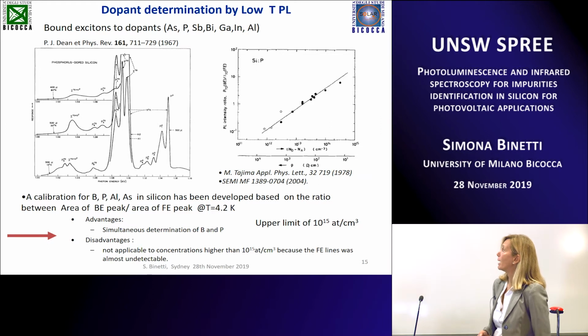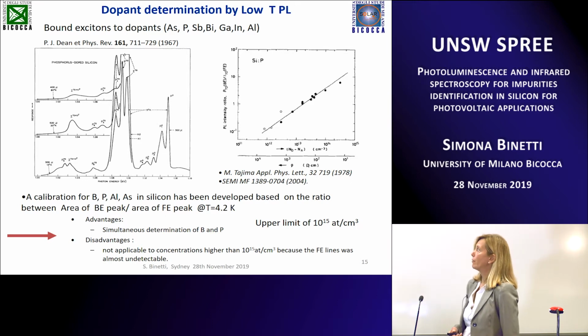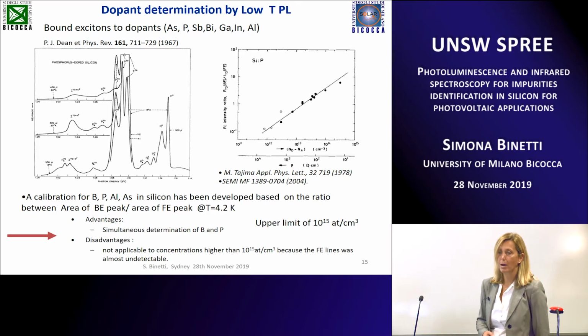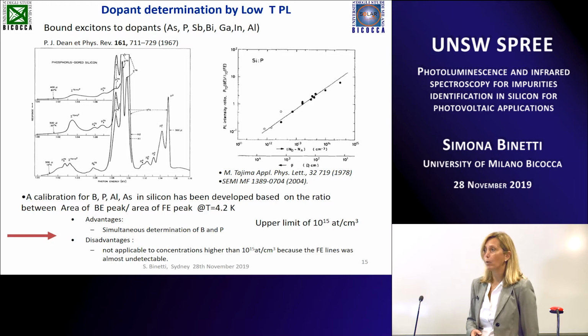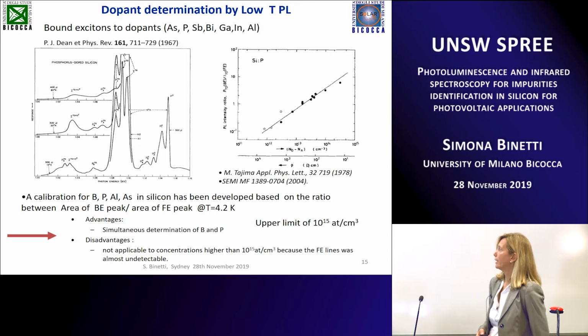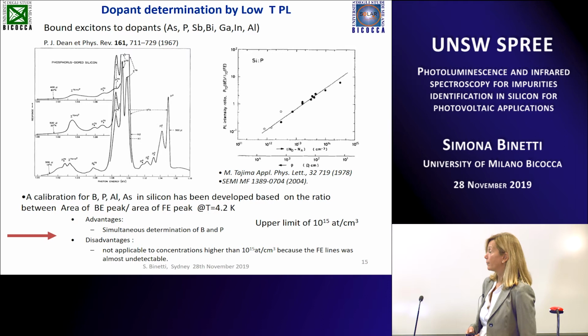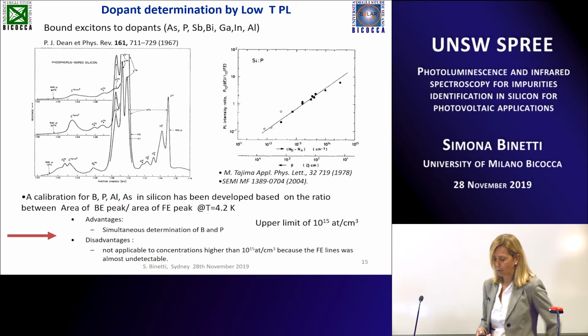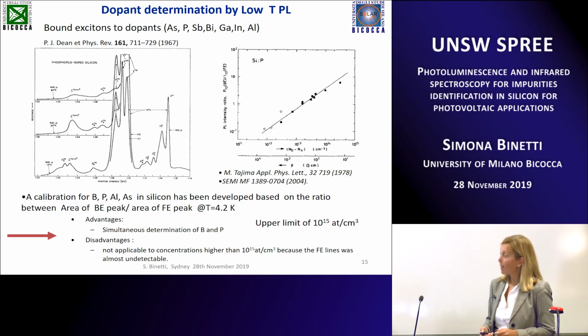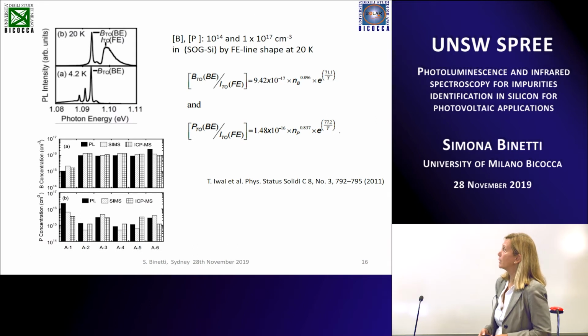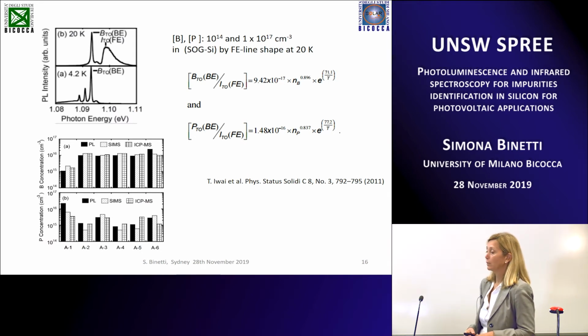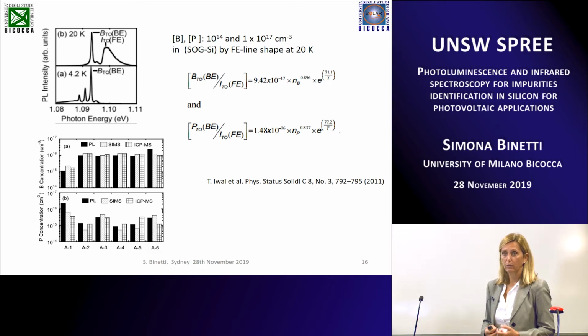This work was done by Professor Tajima in Japan many years ago, in 1978, and there was a very good correlation between the intensity of the bound exciton line and the dopant concentration, with a sensitivity lower than 10 to 10, and the upper limit is 10 to 15. So it means that in the case of multicrystalline silicon, or silicon for photovoltaic, it cannot be used. But recently, the same Japanese group developed a new calibration in order to use this system also for multicrystalline or monocrystalline silicon.